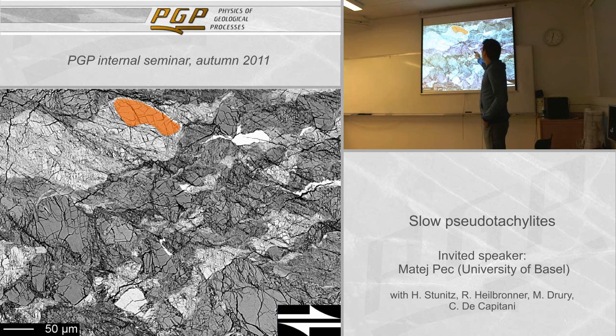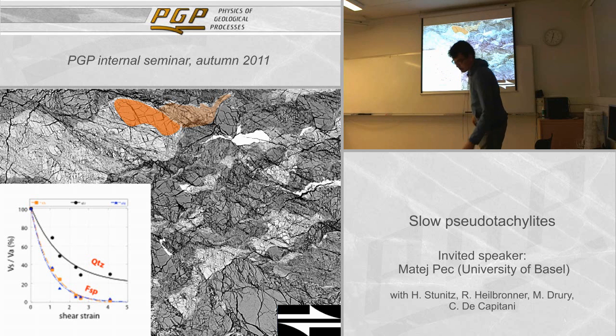survivor grains are larger and survive in between the Riedel shears, and we can also see these so-called fragmented mantles, as we call them, which is extremely finely comminuted material. All this together has a synthetic orientation with the induced sense of shear, and we call those aggregates of one phase that are delimited by face-to-face contact. So we can quantify this to see how the individual minerals fracture, and this would be the survivor grains to volume of the aggregates ratio.